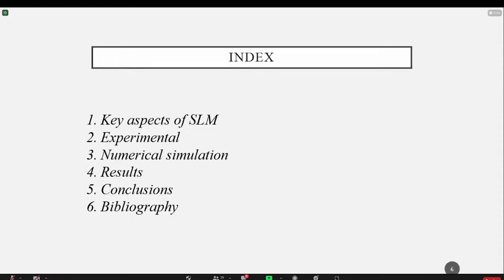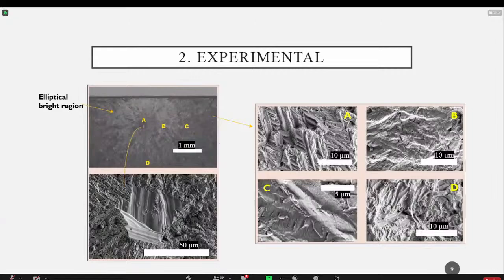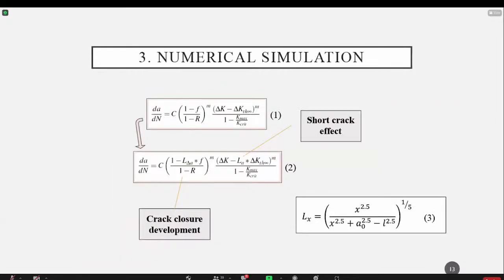I have just one last question. In the slide that you were presenting the equations that were used, the first one is, if I'm not wrong, what we know as the NASGRO equation. That's correct. And usually the constants for this, we find either in the literature or in the software called AFGROW. How did you find these material properties for this AM part that you tested in the lab? We found a few papers in the literature that were specifically related to additive manufacturing. Okay, and they calculated the constants for this equation. Exactly. They should be at the end in the bibliography. I don't know if they're there, but they should be there. Thank you. I will refer to that.